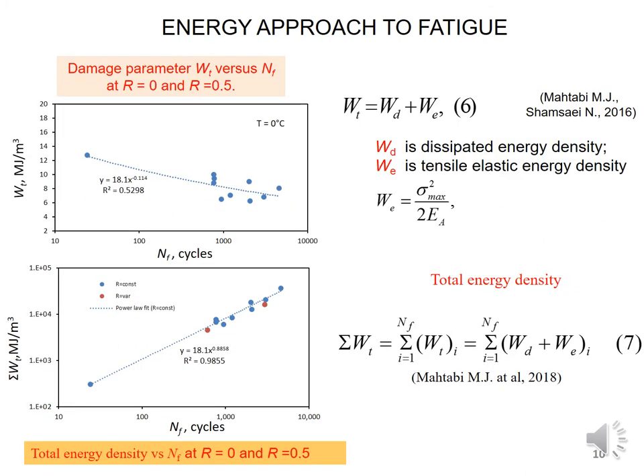The upper figure shows the dependencies of the damage parameter on the number of cycles to failure at both stress ratios 0 and 0.5, calculated by Formula 6. The Young's modulus of austenite and maximum stress were used in the stabilization region for calculation of elastic energy density. Another energy-based criterion of fatigue failure could also be used — based on the sum of total energy density and calculated by Formula 7, as shown on the lower figure. This parameter is in good agreement for various cyclic loadings, stress ratios, and two-step variable amplitude loading.